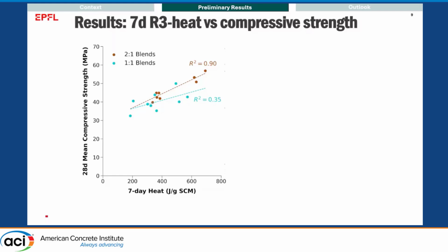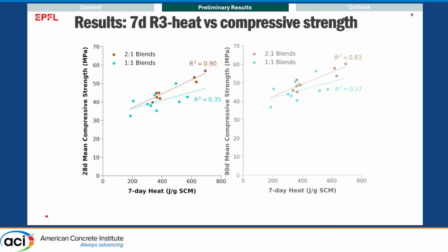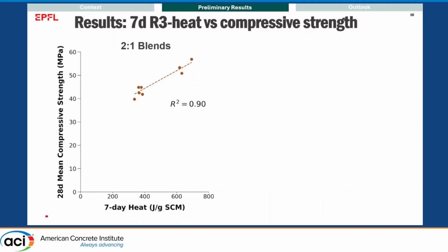You can clearly see that the correlation is good for the 2:1 blends between 7-day heat and 28-day strength, while the correlation for 1:1 blends is bad. And the same story is repeated when you correlate 7-day heat and 90-day compressive strength, where R-square values decreased a bit, but more or less it is the same, that 2:1 blends are very well correlated. Let's take a closer look at 28-day compressive strength versus 7-day heat, and this is the trend line that I showed.